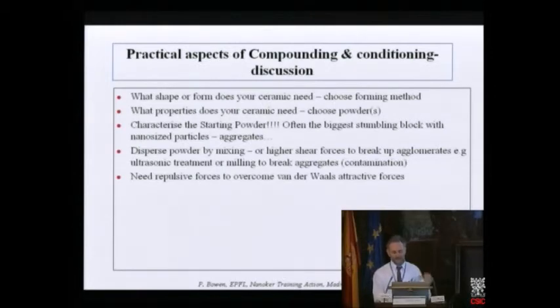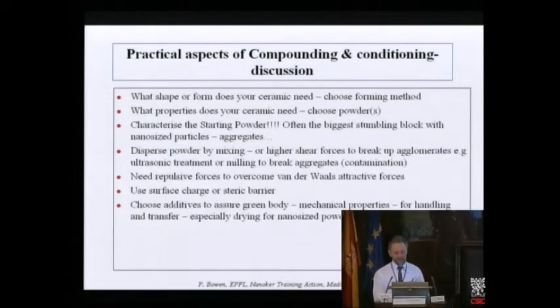You need repulsive forces to overcome the attractive van der Waals forces. We'll talk a lot about that on Friday. You need surface charge or a steric barrier. You choose your additives to assure the green body has mechanical properties for handling, for transfer, and like I say, especially for drying of nanosized powders, you need additives or you need clever gel casting approaches.